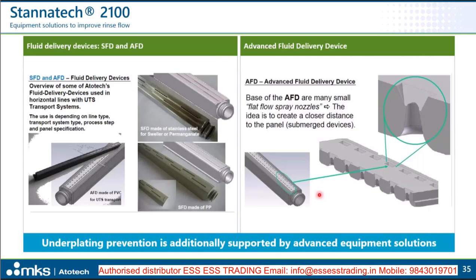And finally, I think it's not only about chemistry, but it's also about the equipment. You are aware we are also offering the horizontal systems for the immersion tin plating. So I would just like to mention that it's not just a flood bar for the rinsing and also for the immersion tin plating process, but there is a lot of engineering know-how behind the fluid delivery devices in the plating module as well as in the rinses, to ensure that we have the best, let's say, agitation and really bringing the chemistry and the water right there where it is needed. And there are, let's say, different systems and approaches which really ensure the best solution exchange and rinsing conditions to clean the panels after the plating process.